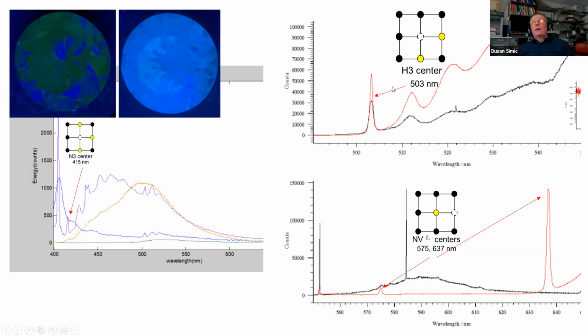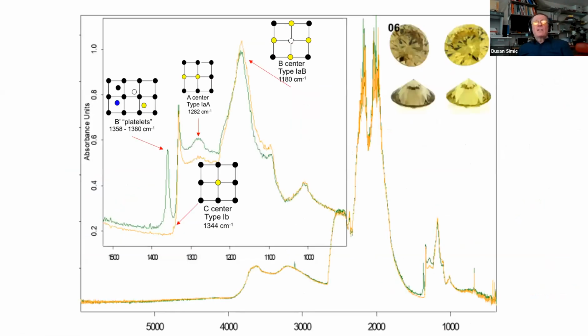And in the 514 photoluminescence, we see again a significant change in the aggregation, like the H3 center is decreased or partially annealed. And what is most important, it is the NV centers. They are giving us enough information that this stone is treated. It is not enough in general, but in this case, it is enough to say this stone is treated.